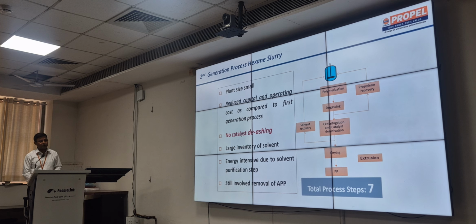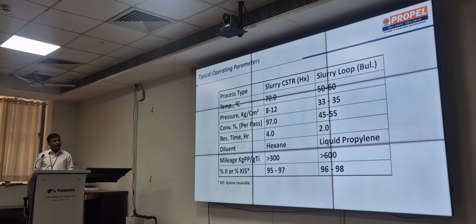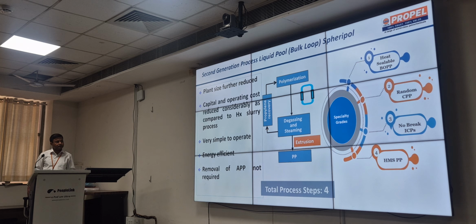In the second generation, from 8 to 7 steps, no catalyst de-ashing is required. If you compare the process parameters, the slurry loop you can run at much lower temperatures. Conversion in the CSTR case is much better, 97%. In the second generation, again, the plant size has been reduced from 8 to 7 to 4.